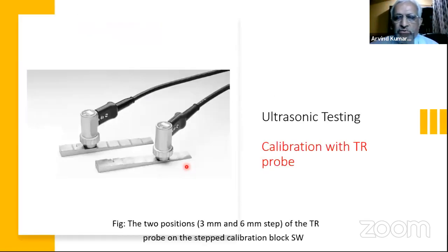So what we need to do to calibrate this TR probe is, suppose I want a range of say 10 mm, I have to always use 2 thicknesses. In this case, I am using 3 mm, this is a step edge block. Each step is 1 mm say. So I'm using 3 mm here and 6 mm here. I keep the probe on 3 mm and see on my screen whether I'm getting a 3 mm reading. Then I put the probe on 6 mm and see that I am getting 6 mm.